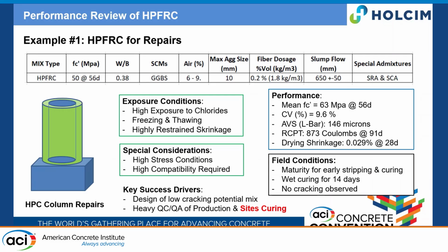So basically, the first example I'm presenting is a repair we had to do on a high performance concrete column. We had to do a jacketing. And for that, the exposure condition was high in chloride. So in Canada, we use the class that is called C-XL, so it's highly exposed to chloride, saturated, and with freezing and thawing exposure. Because we have a repair, the other component is that we have highly restrained shrinkage conditions.